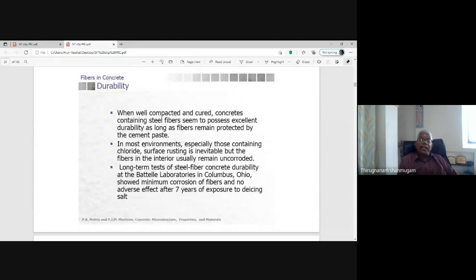Durability. When well compacted and cured, concretes containing steel fibers seem to possess excellent durability as long as fibers remain protected by the cement paste. Only the fibers exposed on the surface will be corroded, but the interior fibers are giving the excellent durability. In most environments, especially those containing chloride, surface rusting is inevitable, but the fibers in the interior usually remain uncorroded.